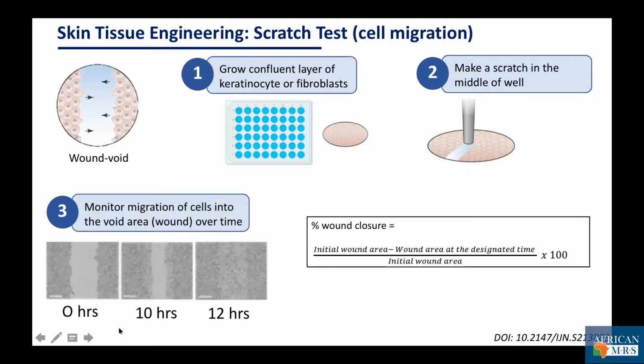So here we have optical microscope images showing how the wound or void area is progressing over time. So at T0, you can clearly see the void area, and as time goes by, you can see that the void area is filling up with cells. And we can calculate the percentage wound closure using the following equation.